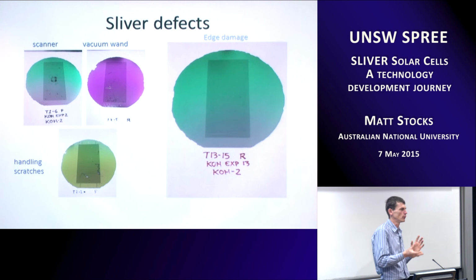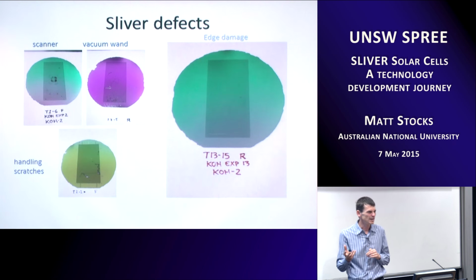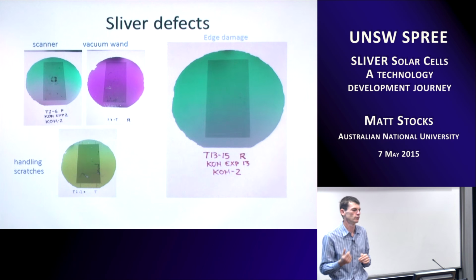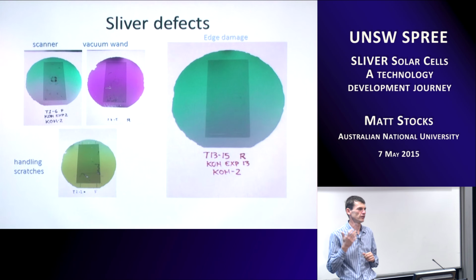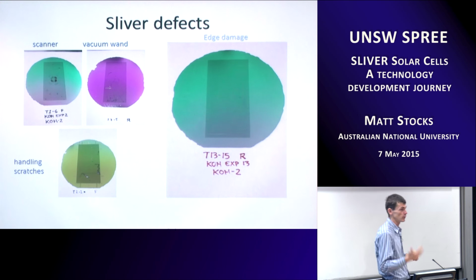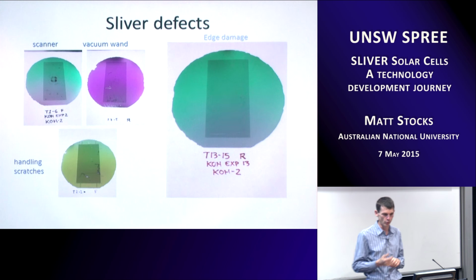In solar, we're a little bit more interested in both sides because we'll put a back surface field or some PERC contacts on the back, but pretty much the rear still is pretty robust. And what we found here was that both equipment and people handling things meant that we were actually getting a lot of damage on the rear of the wafer.